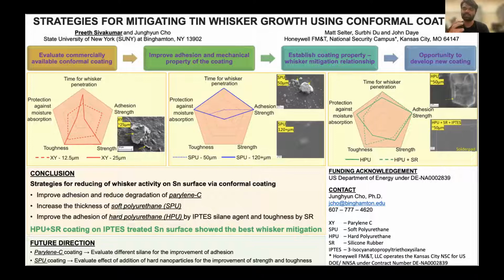So this relationship would help in developing new conformal coatings in the future that can effectively mitigate tin whisker during the long-term aging. Basically what we found out was the relationship between the strength, toughness, adhesion strength, and protection against moisture absorption. All of them played a huge role in extending the time for the whisker to completely penetrate through the coating. So we evaluated the effectiveness of parylene at 2 different thicknesses, soft polyurethane, which is urethane, at multiple different thicknesses, and hard polyurethane with and without silicon rubber to see the effect of the increase in toughness and also the increase in the adhesion strength.